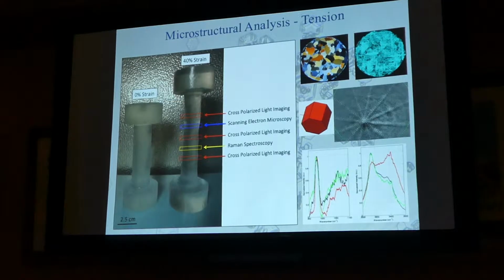And for the dog bone shaped specimens, we would do similar. We would do the cross-polarized light. We also did Raman spectroscopy. I'll talk more about that in a minute. And also looked at it in the electron microscope. And so here's an untested sample, 0% strain. And this is what a sample looks like after it's been stretched, 40%.